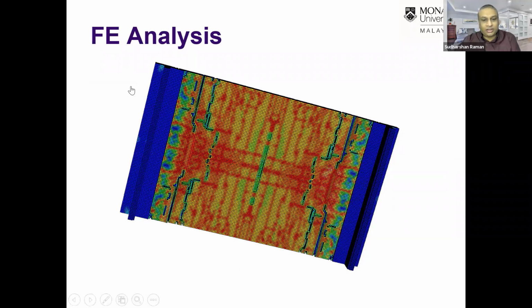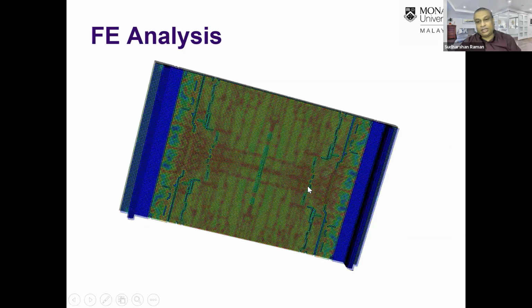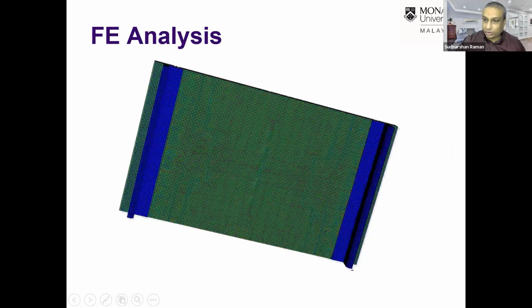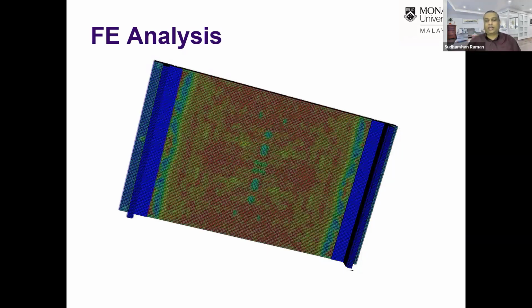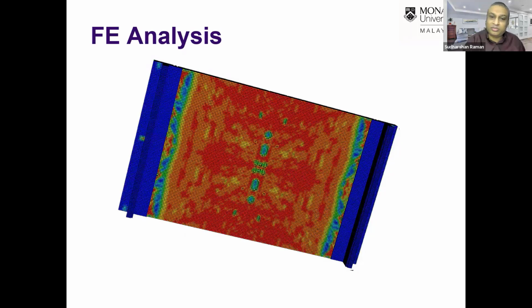This is the bottom face of the panel, and in the polyurea coated panel by 4 millimeters, what we initially observed was that the polyurea layer was still intact. Even in the test, we did not notice any tearing of the polyurea, and we did not notice any debris and fragments being propelled. When we remove the layer, we can see that the damage mechanism has changed, but there was no debris and fragment produced, mainly because the polyurea layer was still intact.